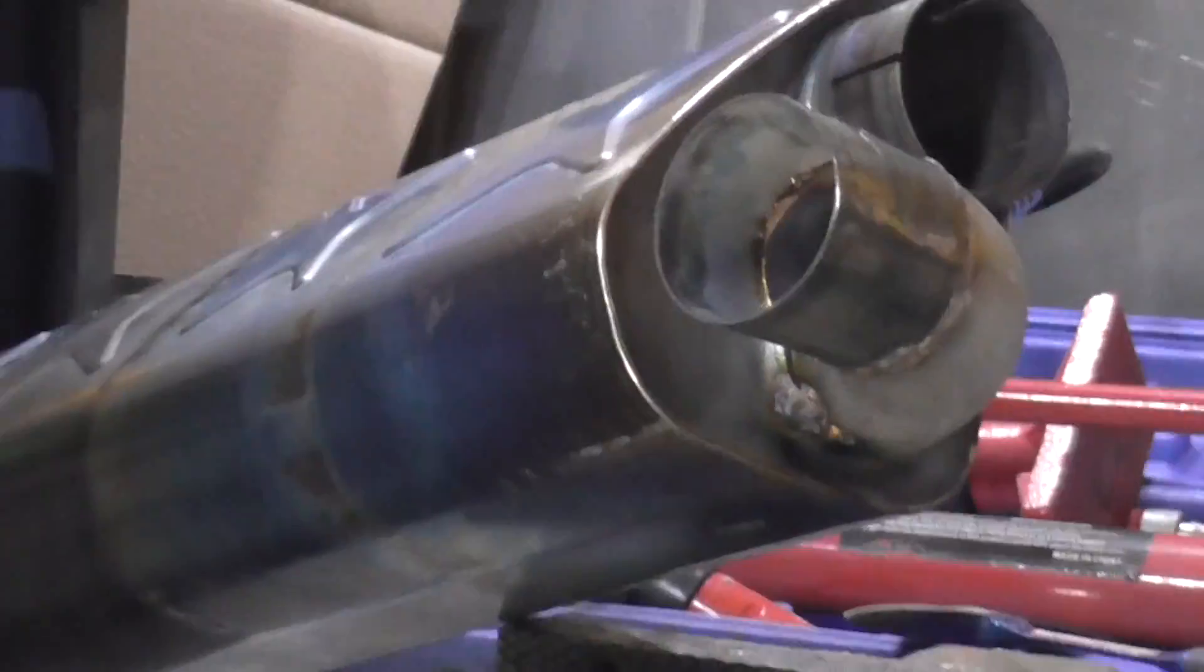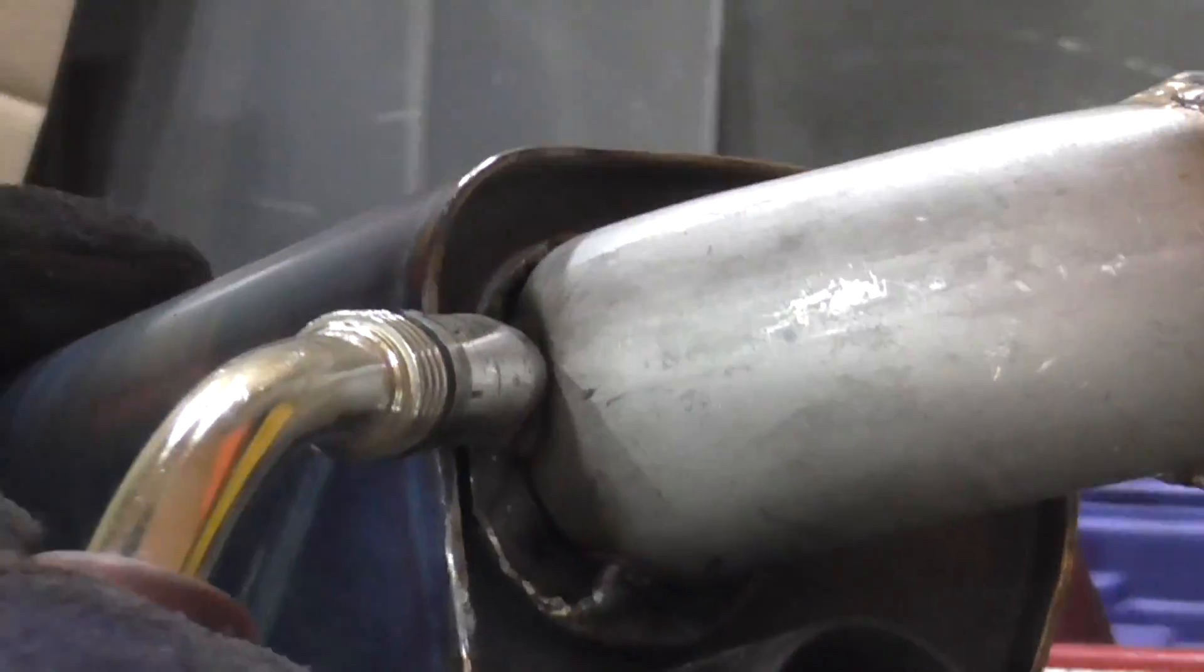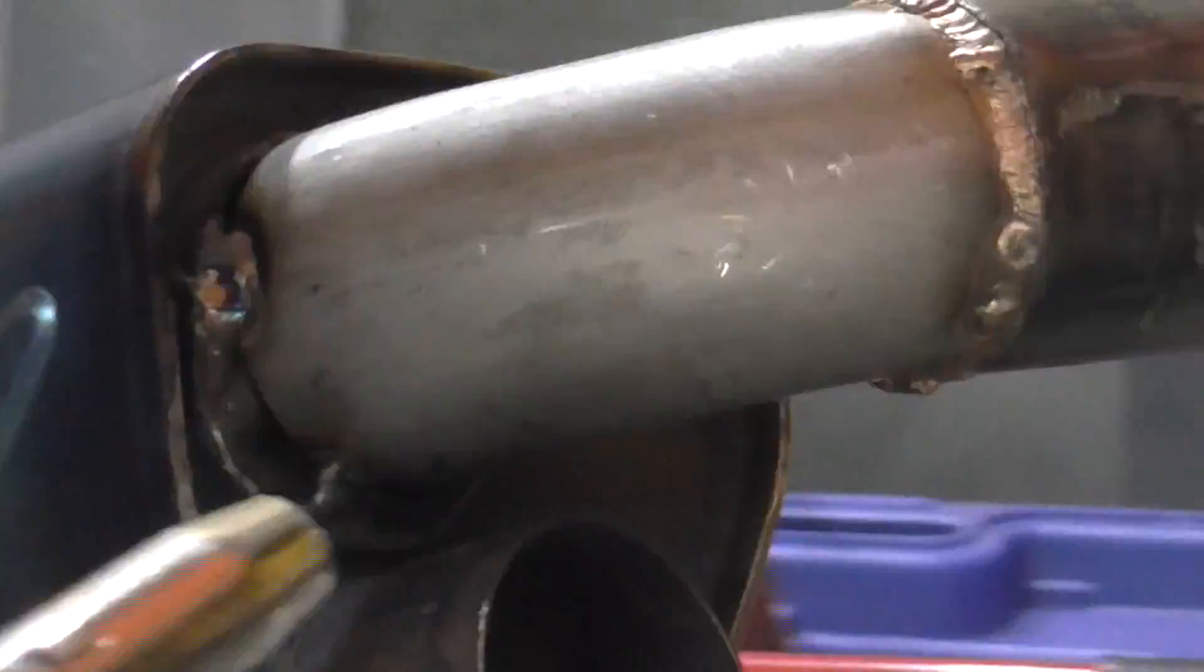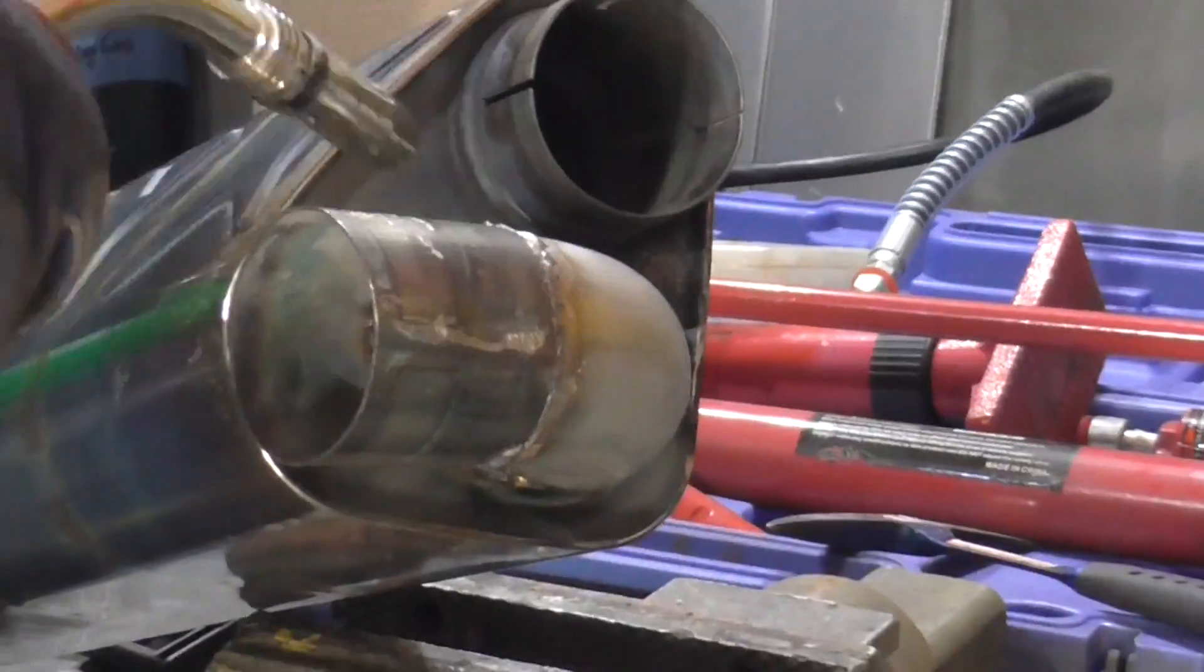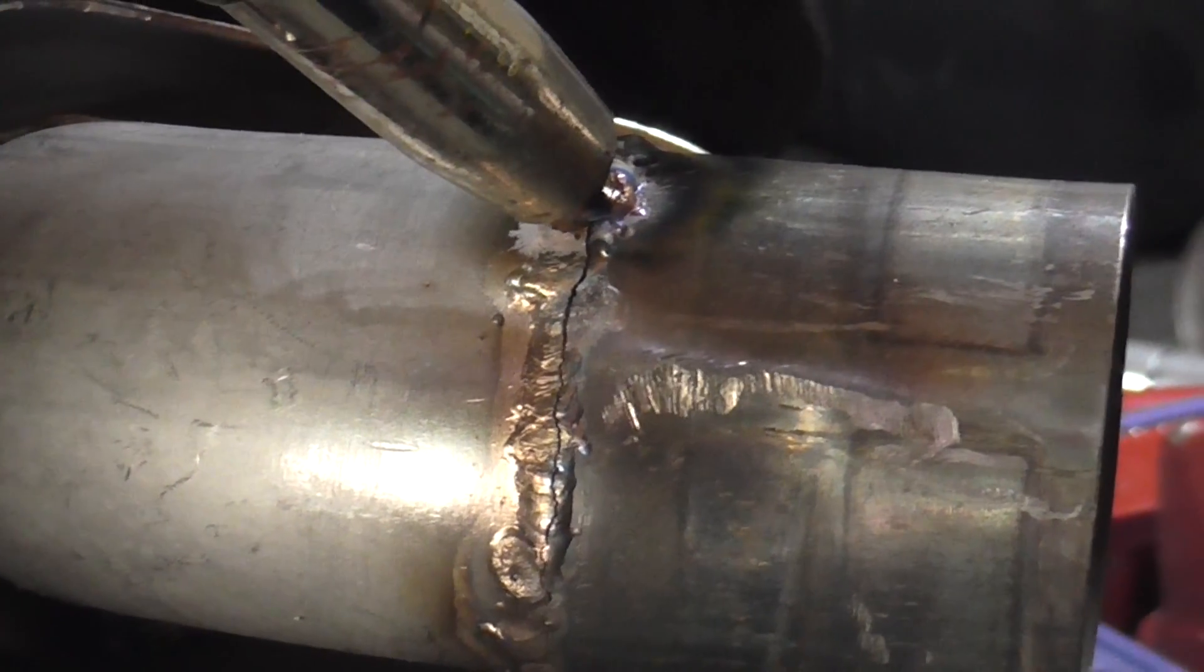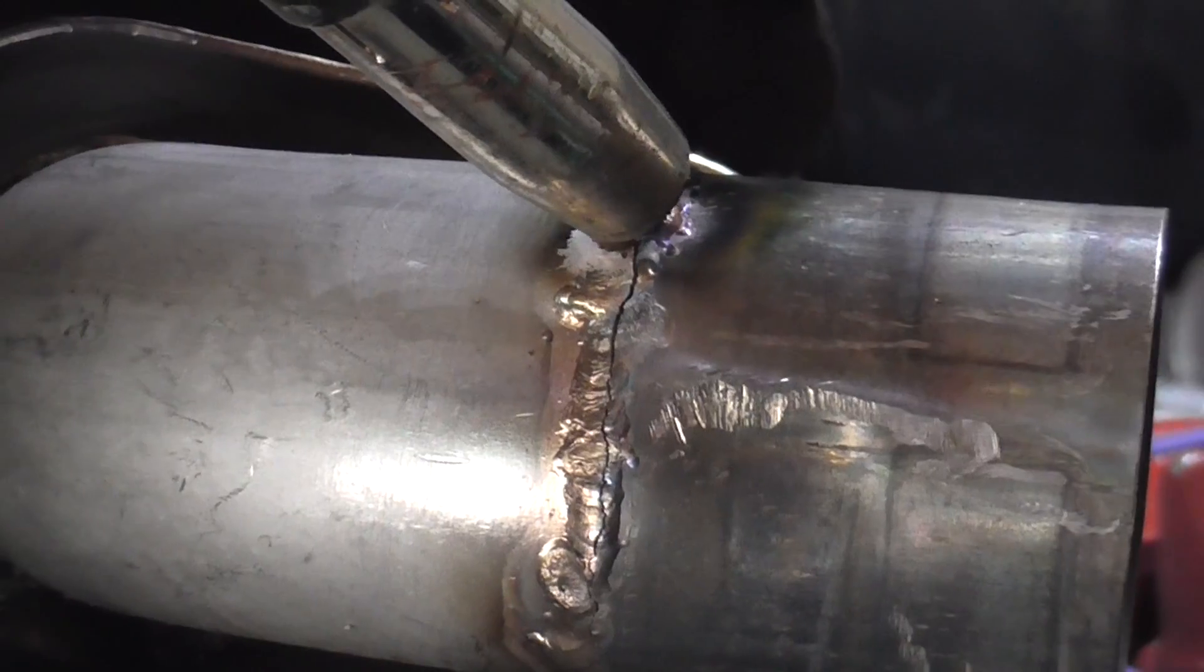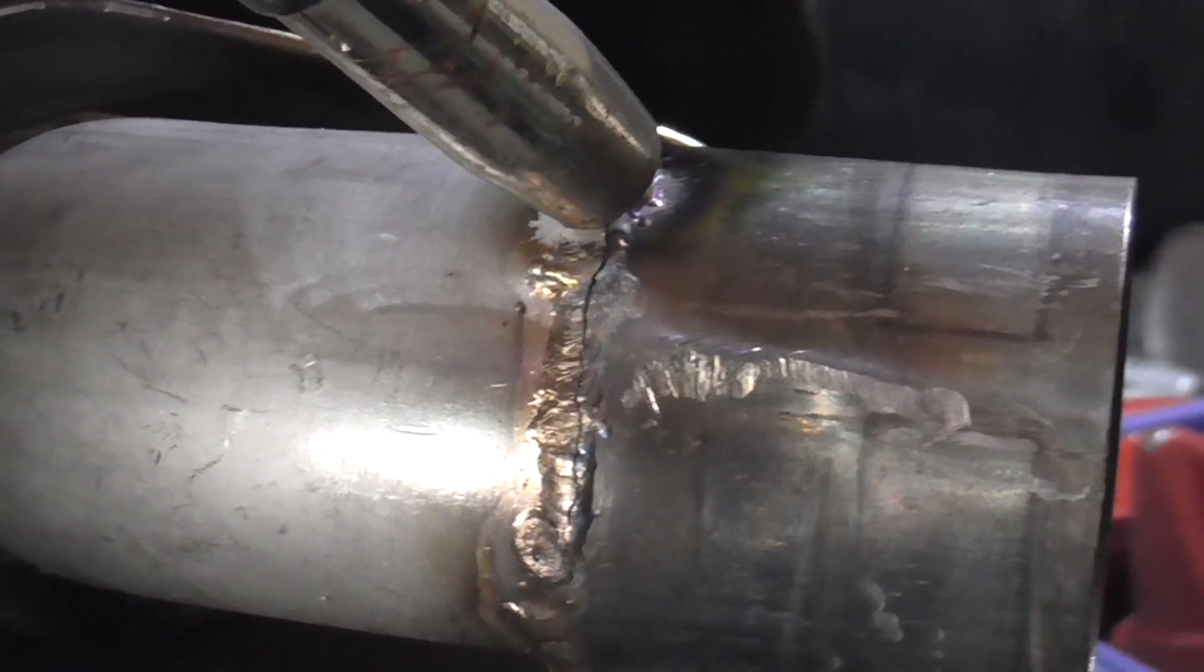This has sped up quite a bit here. Although it feels like I'm taking large breaks between tacks, you don't want to make any welds longer than a quarter inch at most. At the beginning I got a little lucky, but what happens if you weld too fast? See this crack right there? As it cools down it just stress cracks.